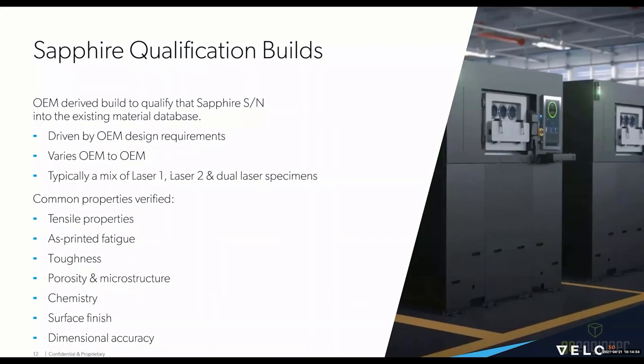Typically, these are a mix of laser one, laser two, and dual laser specimens. And I just have a list here of what we commonly see with these. So tensile properties are basically always there. Oftentimes designs are limited by fatigue, and so fatigue is often verified. Toughness comes up as well. And then generally there's always a process cube in there for verifying the lack of porosity in the microstructure, chemistry, surface finish, and dimensional accuracy. This is a little redundant with a site acceptance test build, but many OEMs want to just have that level of consistency where they're tracking it on their Sapphire qualification build reports as well.